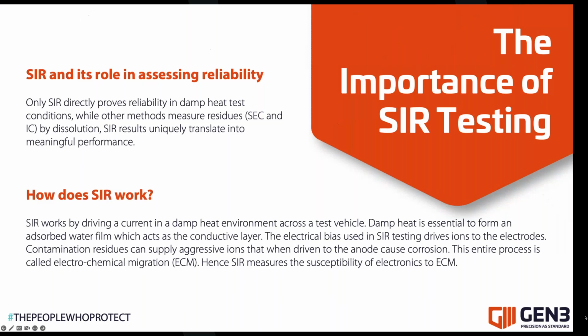So one of the really important things about SIR testing compared to anything else is that it's measuring an electrical parameter. It's measuring the leakage current. So it has real meaning in terms of how a future product is going to perform in the field. It's not just telling you that there's a certain chemistry on the board, which may be important, but it may not. And the SIR pattern is geographically located in particular positions, and it can be part of a component termination set, or it can be underneath a component. So we also know where the SIR issue is because we're measuring a pattern which is related to a component.